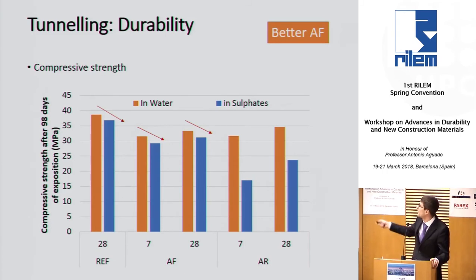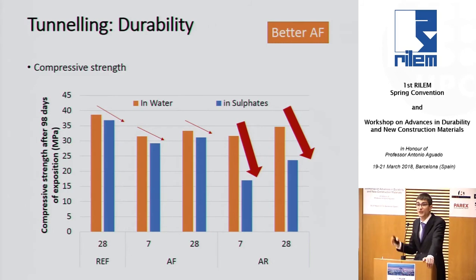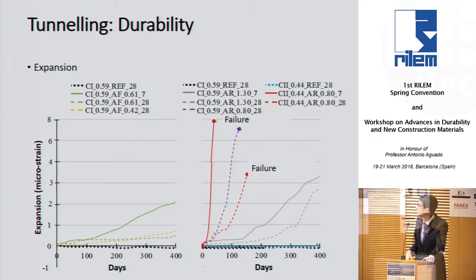So you have a very big reduction in performance, which is very big or even bigger for the mixes with alkali-rich accelerator. So a first important result here: we need to use alkali-free accelerators. It's not a problem in most of Europe, but here in Spain particularly, we have been using a lot of alkali-rich. It's the main accelerator to use. So it's a problem for the durability, right?